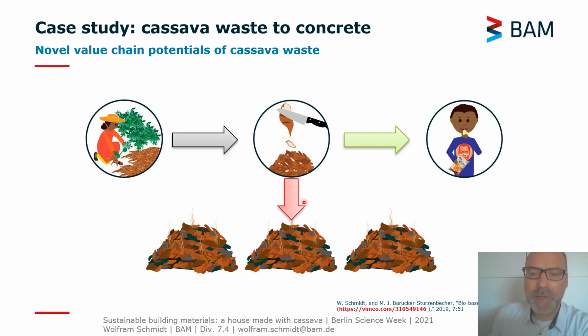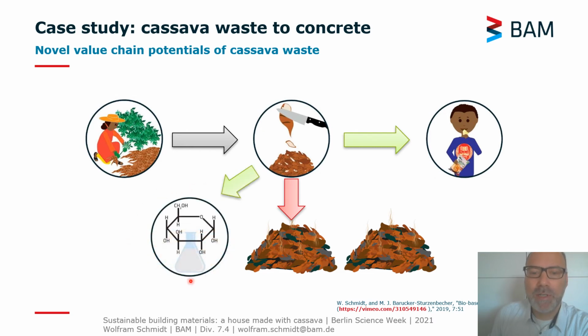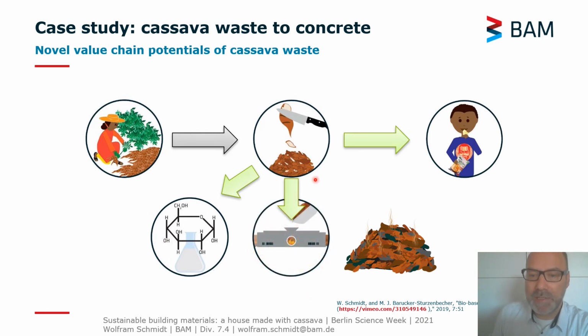And instead of considering that as a waste, as a useless waste, it's possible to first derive the easily soluble organic components, mainly starch, from these waste peels and convert it into a superplasticizer to reduce the water content in concrete, and this way to tickle out more performance of the cement, and this way save overall cement in concrete. And then the residual peels, after obtaining the starches, can still be burned.